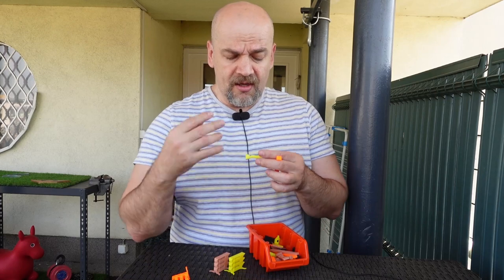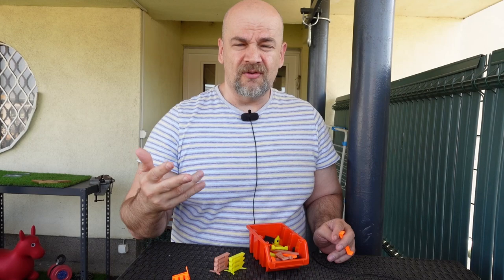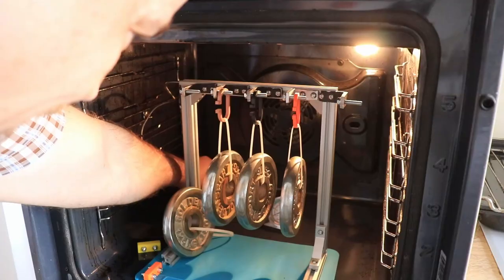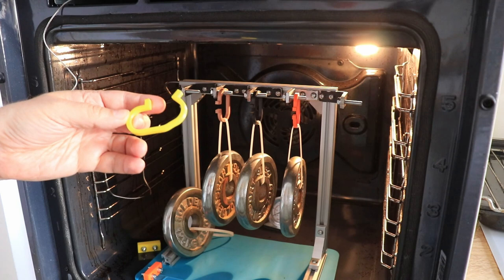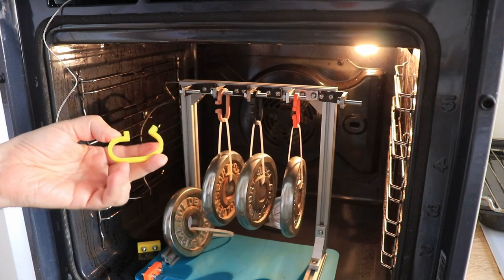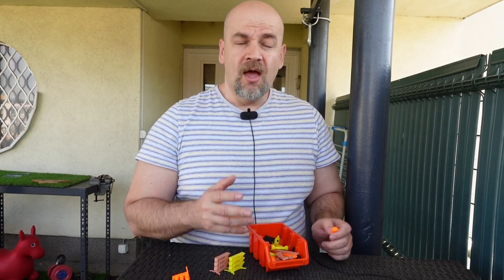About the materials, yes, the PLA is, as expected, a very strong material, but you saw it cannot resist high temperatures. Actually, it cannot resist temperatures above 30 degrees Celsius if you put it under constant load, that's the creeping. But above 50 degrees Celsius it will deform under any kind of small load. For that you want to move to the PETG, which is not as strong as the PLA, but it is less brittle. And it can resist temperatures up to maybe 70 degrees Celsius. But it is also very easily printable, you don't need an enclosure and similar.